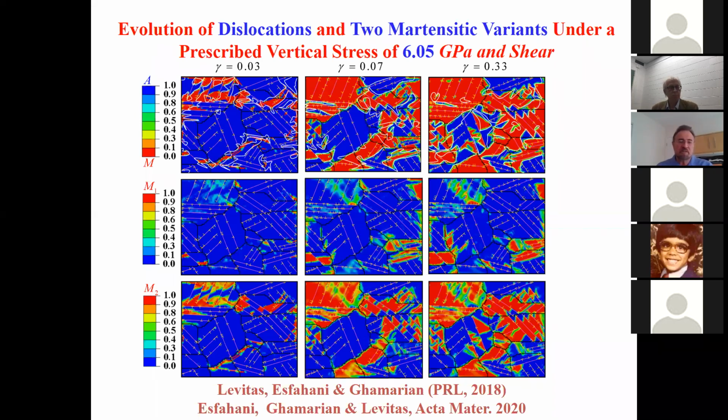the group of Vladimir Blank from Troitsk studied it. At least I remember some experiments at slightly elevated temperature and at cryogenic temperature. I don't remember honestly the comparison of how this effect works for different temperatures. But generally, an increase in temperature should reduce this effect and finally eliminate it above recrystallization temperature, and a reduction in temperature should promote this effect.